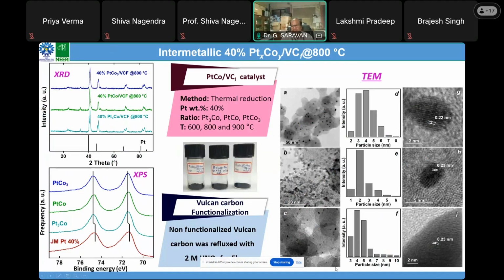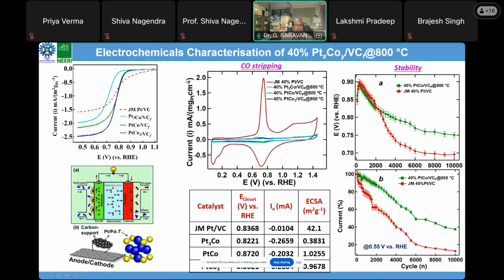And this is the typical TEM analysis, and the particle size is roughly 2 to 4 nanometer, and it is a highly ordered structure that we got. And we performed ORR, oxygen reduction reaction. The dotted line is the typical commercial Johnson-Matthey catalyst. When you go with the PtCo, and PtCo3, it is much better than the commercial Johnson-Matthey catalyst.